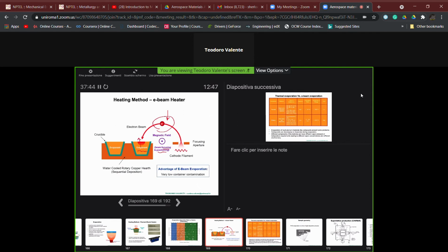That means evaporation by electron beam, not using heat, not using resistance, not using the Joule effect, but just using the dissipation of energy, which is related to the fact that an electron beam is focused and pointed on the surface of the target materials. The advantage of this method with respect to the other one is that, since we focus our beam directly on the source materials, essentially we can expect, and this is the case, a very low container contamination on the finally fabricated coating.